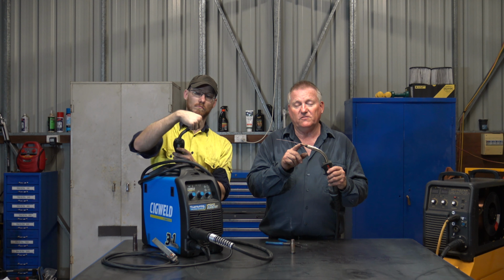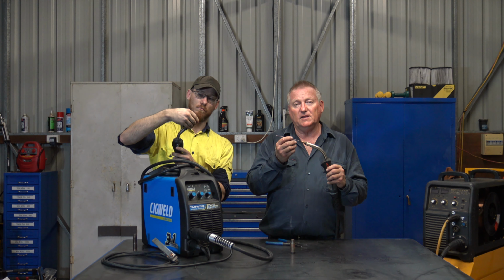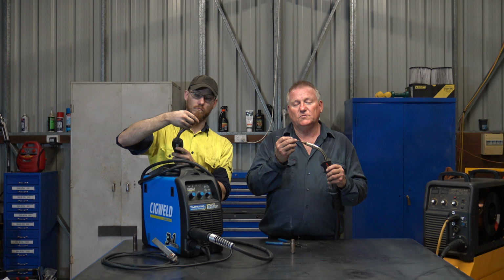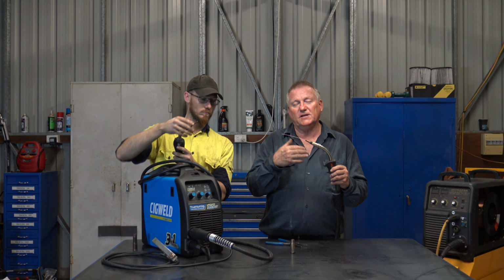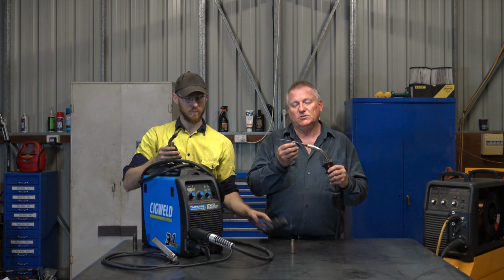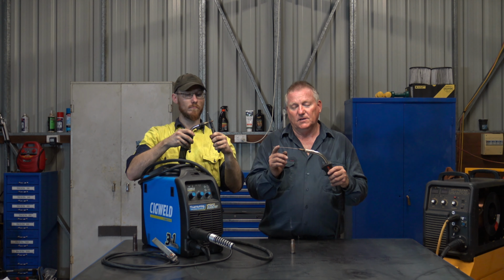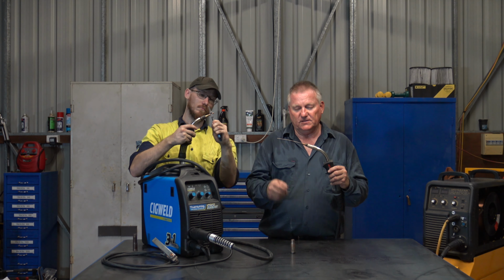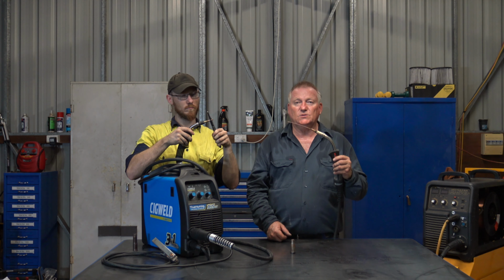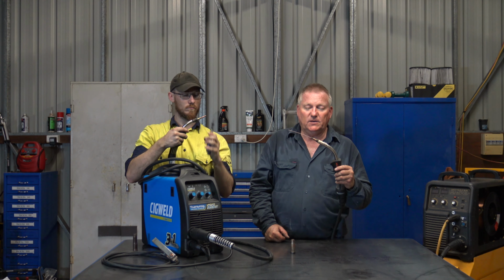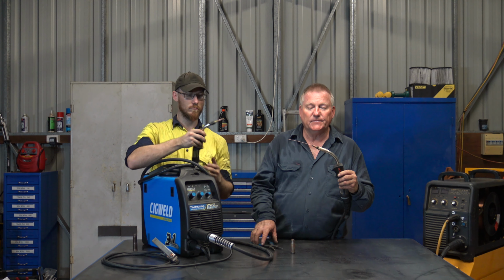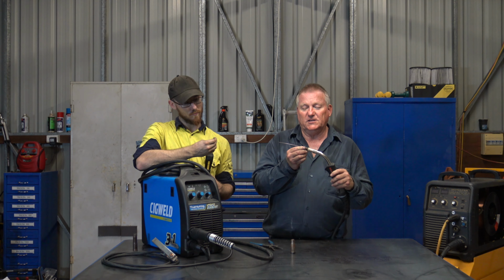It does wear out over time, so if you get an oval shaped hole in there, you can get too much play in the wire, and then you can have arcing inside the tip, which stops the wire, and then the wire will burn up and melt onto the end of the tip, and it's very difficult to then get the tip out and replace it. Contact tips are not overly expensive, so make sure you replace them when they need to.